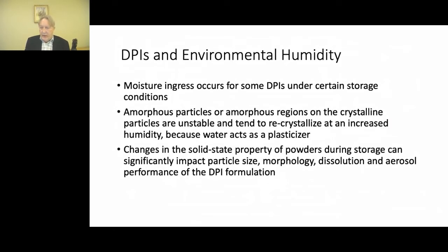So, DPIs and environmental humidity: moisture ingress occurs for some, and I would say most, DPIs under certain storage conditions. Essentially what happens is amorphous particles, or amorphous regions on the crystalline particles, are unstable and they tend to recrystallize at increased humidity because water acts as a plasticizer. The changes in the solid state property of DPIs during storage can significantly impact particle size, morphology, dissolution, and aerosol performance of the DPI formulation.